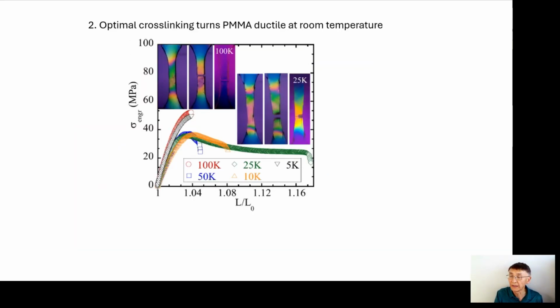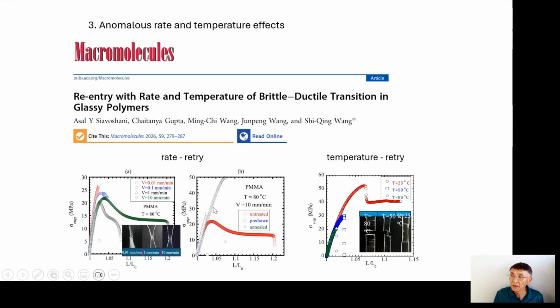This is circumstantial evidence. If you have a brittle PMMA, if you cross-link it to an optimal level, it turns ductile. So this is actually a recent paper published this year. So preventing the pull-out through cross-linking currently works. There's more crazy things. This again published just now: usually based on conventional understanding, if you draw your polymer faster, you tend to encounter brittle response, where you have ductility at the lower rate. At a higher rate, it turns brittle. Now we see the reversal. If you have a certain rate that's ductile, if you lower the rate, it turns brittle.